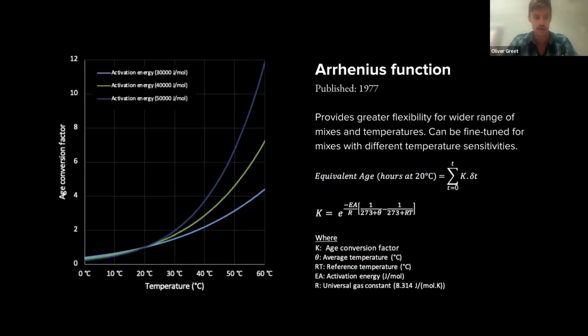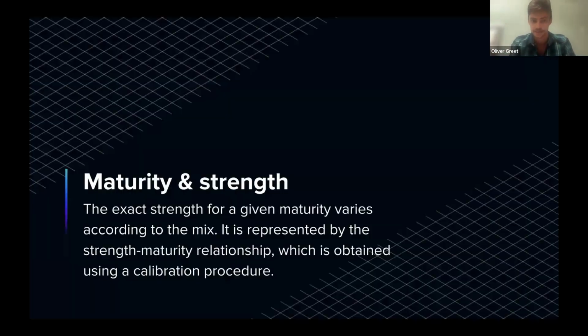So this most commonly in the UK manifests itself when we're curing in cold weather conditions, with high GGBS concrete slowing down more than a Portland cement concrete. It's not broadly known, but conversely, when you move up the temperature scale, you get this massive elevation in temperature with use of high GGBS concretes as well. So it's just a phenomenon of concrete technology that is interesting, and many people aren't fully aware of, that we can quantify exactly how much faster or slower high replacement mixes will be. And that particularly does lend itself, with their increasing use today, to these techniques.